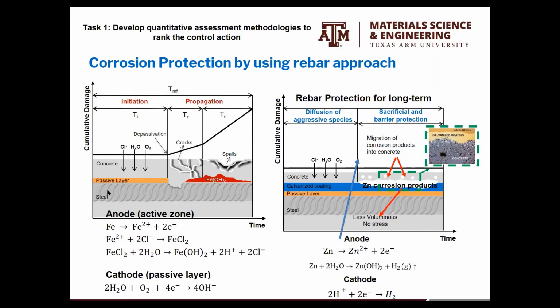I will go very fast because I think that most of you know this: the rebar, the concrete that needs to be exposed to the environment. On the x-axis is time, on the y-axis is cumulative damage. With time, you see that the precursors of corrosion penetrate, migrate, diffuse, and touch the rebar. The rebar has a thermodynamic passive layer. Once it touches, and there is an accumulation, we call it threshold. And when that threshold is met, of course, it depends on the system, then from the initiation part it will go to the transition or propagation, which we call the active state.